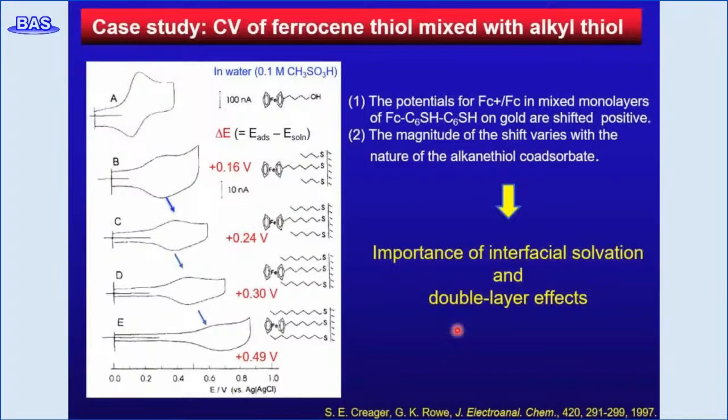In a mixed SAM film of ferrocene alkanethiol and various lengths of alkanethiol, the potential shifts more positively when the head ferrocene is buried in the alkyl chain. This may be due to the simultaneous effect of potential gradient and sorption in the double layers on alkyl groups.